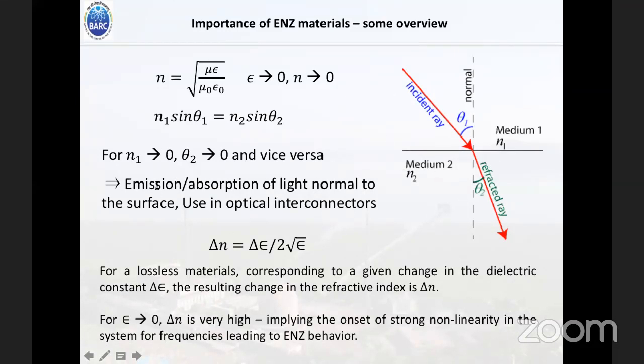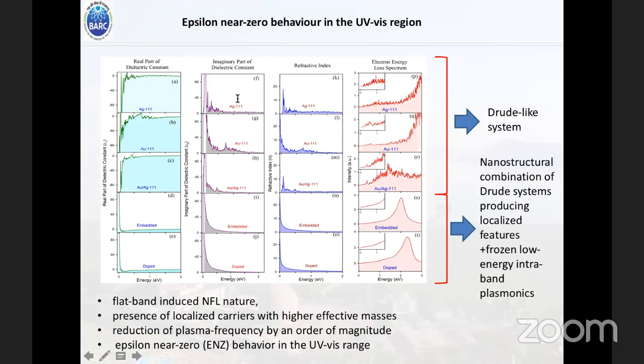So this system can have potential use in optical interconnectors. Also, if you look at this data and simply differentiate this equation, you will see that delta n for epsilon tending to 0 will be very high. That implies the onset of strong non-linearity in the system for those frequencies at which we have the ENZ behavior. Now, for all these three systems, you have this Drude kind of behavior where there is a negative divergence and a positive divergence.